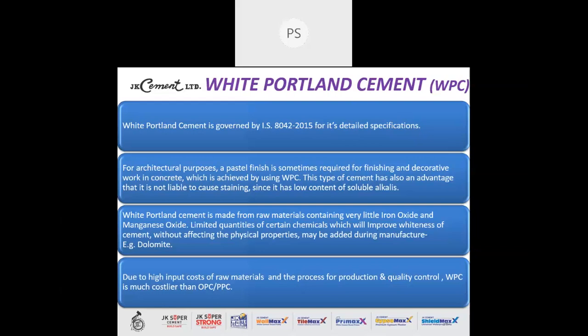For architectural purposes, a pastel finish is sometimes required for finishing and decorative work in concrete, which is achieved by using white Portland cement. This type of cement also has an advantage that it is not liable to cause staining since it has a low content of soluble alkalis. Third point, white Portland cement is made from raw materials containing very little iron oxide and manganese oxide. Now, iron oxide and manganese oxides are the chemicals which impart grey color to the grey cement or the ordinary Portland cement. And as per IS code, you have to maintain a very low percentage of these oxides so as to maintain the whiteness of white Portland cement.